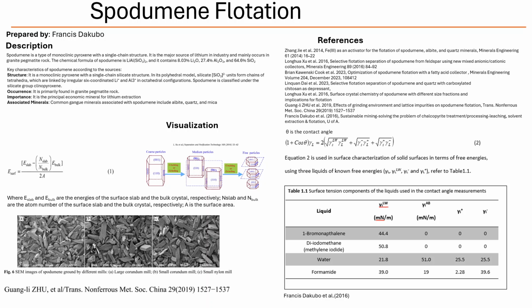Anisotropic, meaning not the same in all directions. Correct. And molecular dynamics simulations back this up. They show NaOL molecules preferring to bind to that 110 plane, likely because it has more of those broken aluminum-oxygen bonds that the collector head group can interact with.